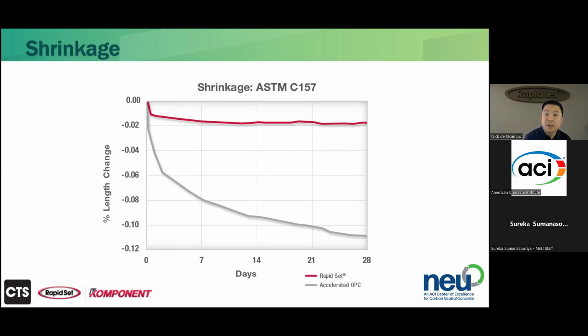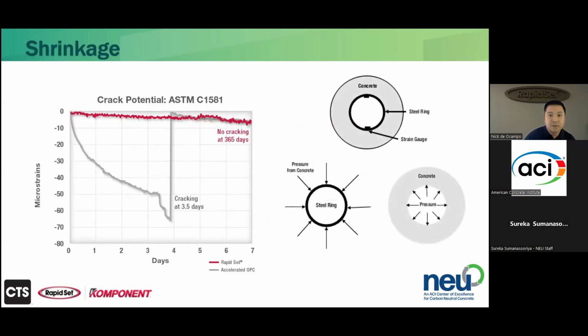However, the accelerated Portland cement shows shrinkage in excess of 0.1% at 28 days. So that's 5 times the amount of shrinkage as the rapid set mix. So we definitely expect the accelerated Portland cement to crack. And we can see that in another test.